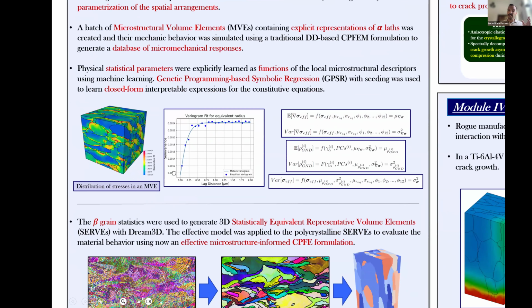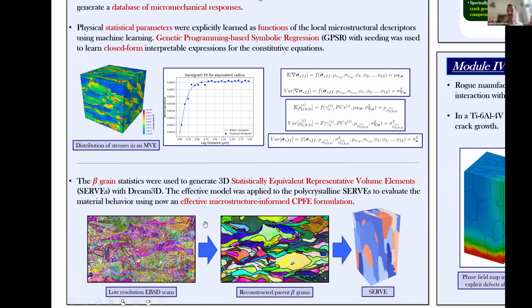On the other level, when we get lower resolution EBSD scans, in a much broader field, and we reconstruct the parent beta grains that gave rise to those laths, we can see the directionality that is natural to the manufacturing process. So we must be able to capture also these characteristics. So we extracted the distributions that describe these beta level grains, and we reconstruct, using Dream 3D, statistically equivalent representative volume elements that we are then able to run using our effective crystal plasticity model. So in these synthetic microstructures, whenever we run the simulations, we encompass the distributions of the microstructure in both the alpha level, the very fine lath grains, and the directionality of the manufacturing on the beta grains.